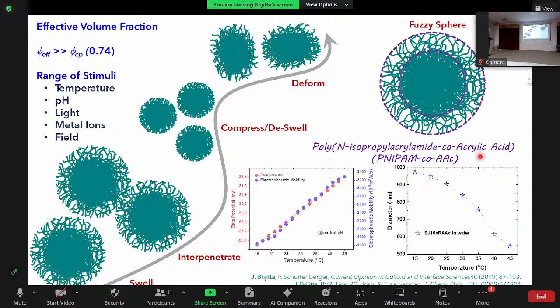And so acrylic acid imparts a lot of negative charge to the polymer chains. So you can see that the zeta potential is quite high for the samples at various temperatures. And this is the diameter of the particles as a function of temperature, and it's about 1 micron.